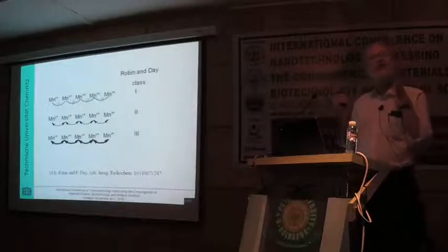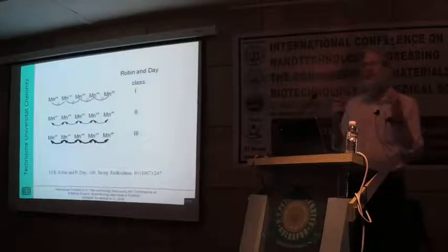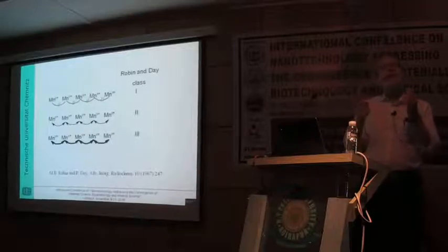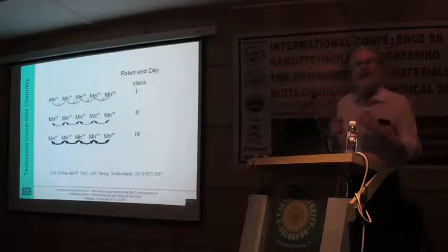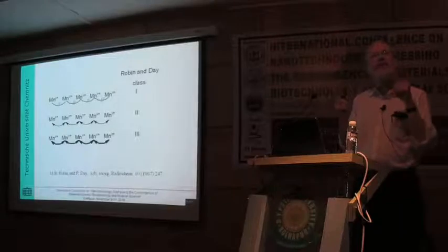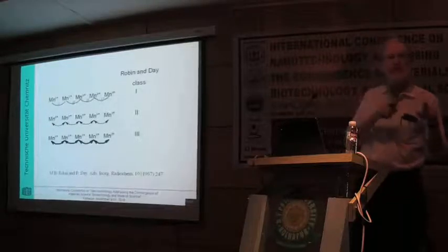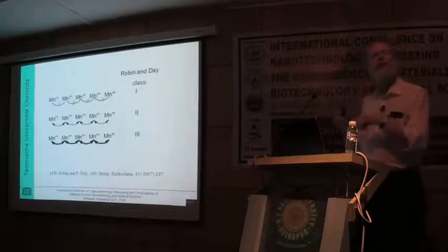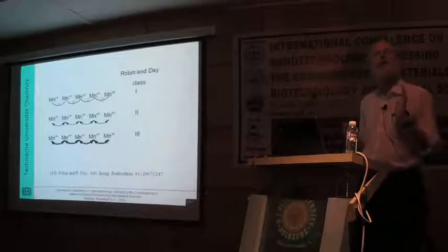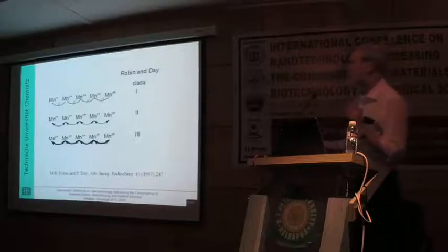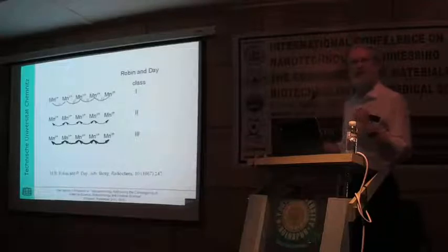If this interaction is very close, I will have a lot of difficulties to remove this next electron. So we talk about a strong electronic interaction between the first and the second and the third and so on, until all the manganese ions are oxidized. That's the case shown here: strong interaction.